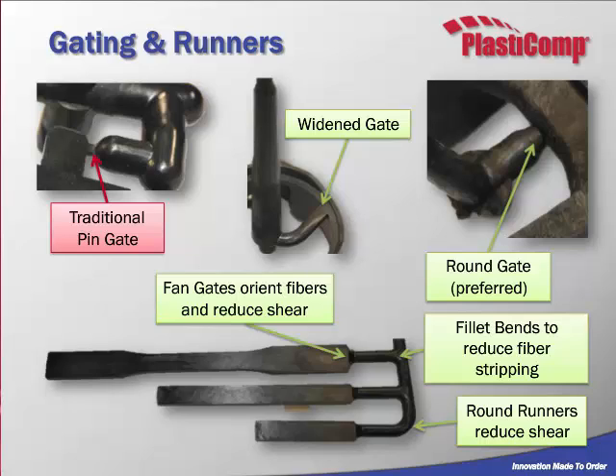Okay, I want to cover gating and runners. One of the challenges you're going to have when using any kind of fiber reinforced material is that you can't have those 1.5 by 1.5 millimeter gates anymore. That starts breaking down your fiber. You can still use it, but your shear forces are going to be much higher, and you're not going to get quite as much out of your fiber strength. We recommend wider gates that you'll typically want to machine off or clip off. That's the downside, but you enhance your fiber length in your part drastically.